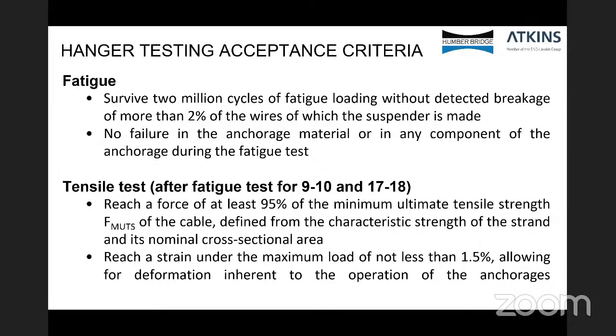Tensile test, it must reach at least a force of 95% of the minimum ultimate tensile strength, defined from the characteristic strength of the strand. Also, the strain under the maximum load should not be less than 1.5%, allowing for deformation inherent in the operation of the anchorages. So we move on to the next slide.